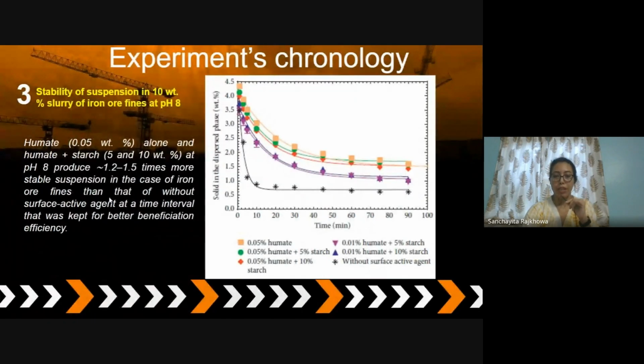Now, in another similar experiment, it shows that humate alone, and humate along with starch at 5 and 10 weight percent, as you can see from these points, at that particular pH can produce around 1.5 times more stable suspension in the case of iron fines than in the case of iron slime. So these are different studies, the setting of parameters through which we can extract more and more iron from the waste materials.